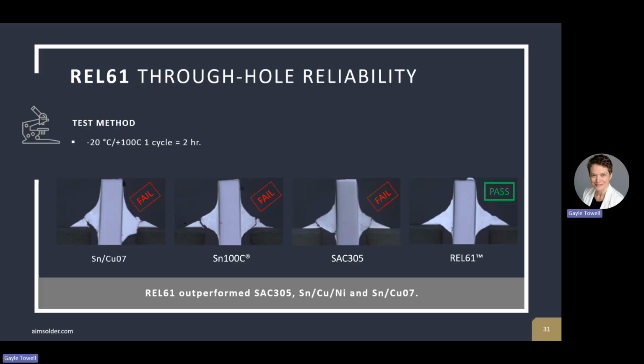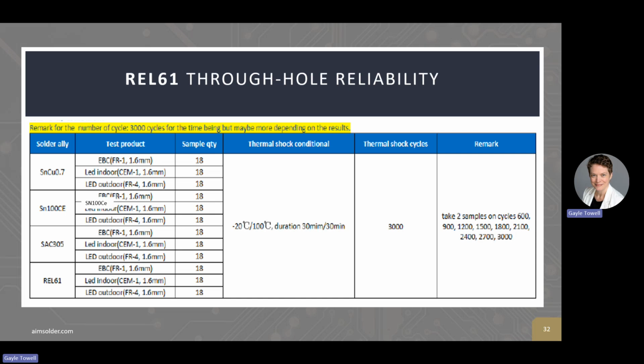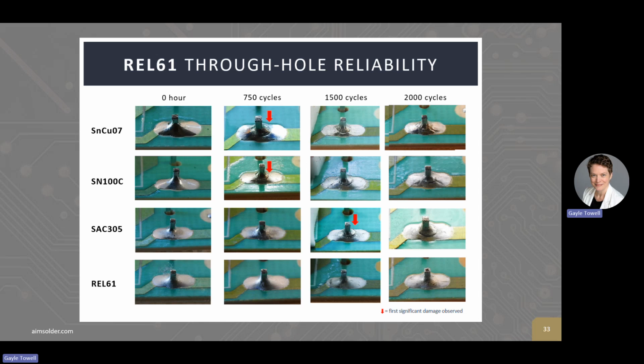Through-hole reliability is another area where REL61 shines, and we just see some images of these joints showing that REL61 creates very nice joints in through-hole applications. This was a test that was performed. These are the results of the test here on this slide. And we see after some thermal cycling, SNCU07 was showing some failures at 750 cycles, as was SN100C. We show SAC305 showing failures at 1500 cycles, but REL61 maintaining its performance through 2000 cycles.